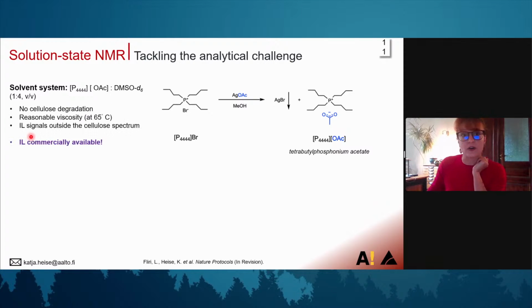However, this one was found to not degrade the cellulose, also yield reasonable viscosity, as I mentioned, at 65 degrees for sample handling. And which is very important, the ionic liquid signals are outside the cellulose backbone signals. And it's also now commercially available, even though it is still very expensive. And following the protocol, you can also do it easily by yourself in your labs.